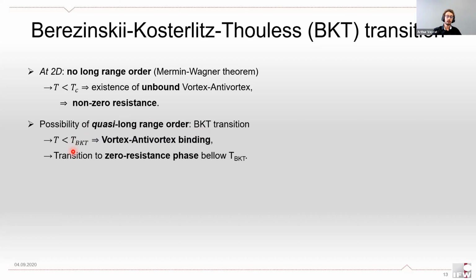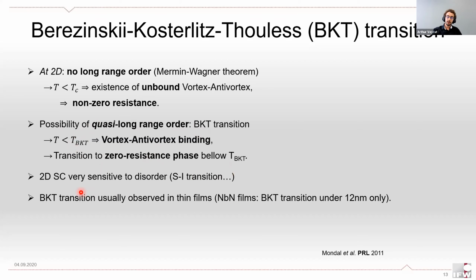So below another critical temperature, the vortices and anti-vortices are expected to pair up and bind together, which means that these pairs will no longer drift when a current is applied, and this will result in a transition to a zero resistance phase below this BKT temperature. The two-dimensional superconductivity is unfortunately very sensitive to disorder, and the BKT transition as well. It has usually only been observed in very thin films. The thickest film which we could find displaying such a transition in the literature was an NbN film of only 12 nanometers thick.